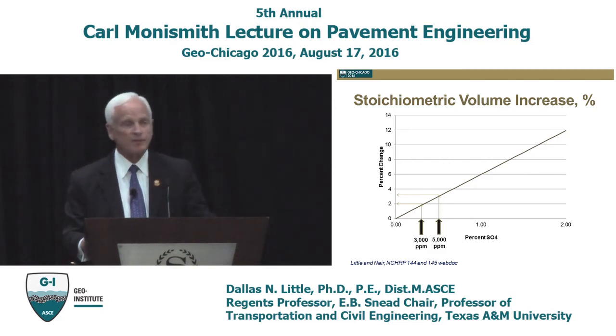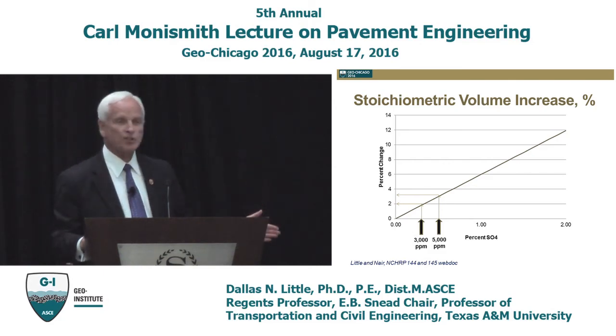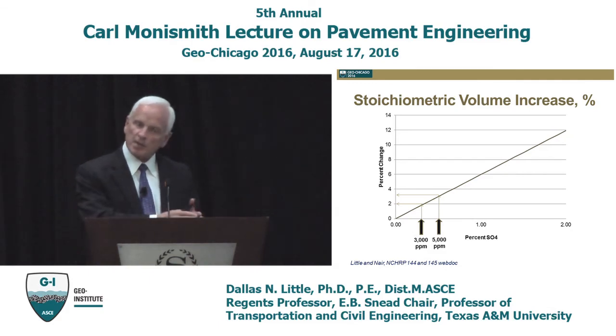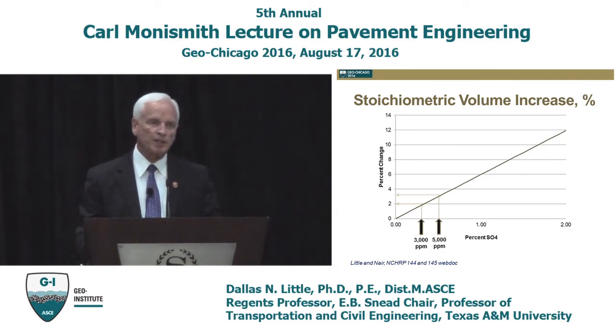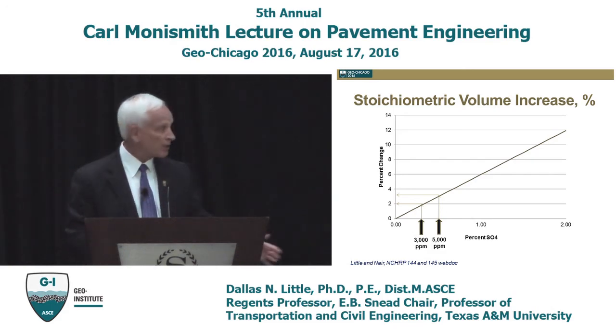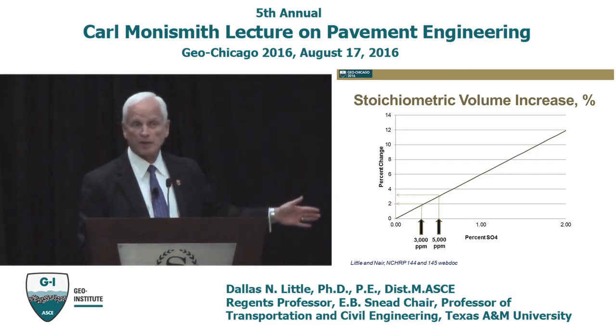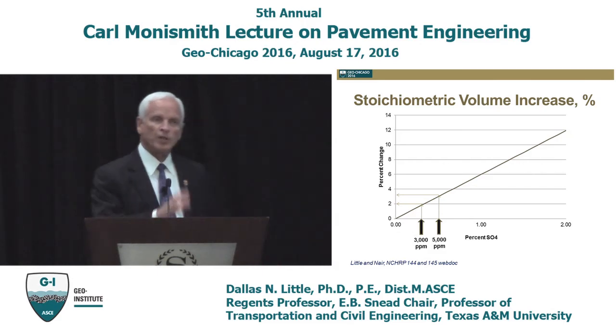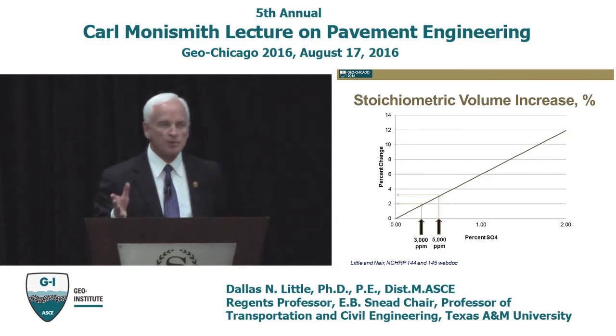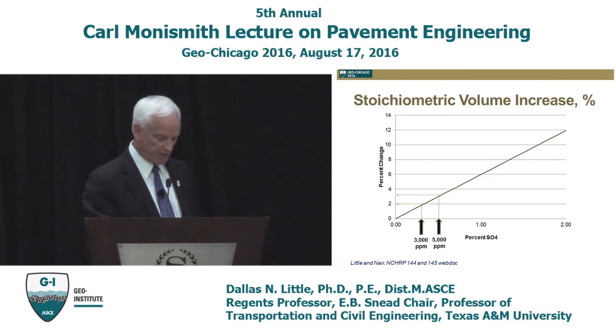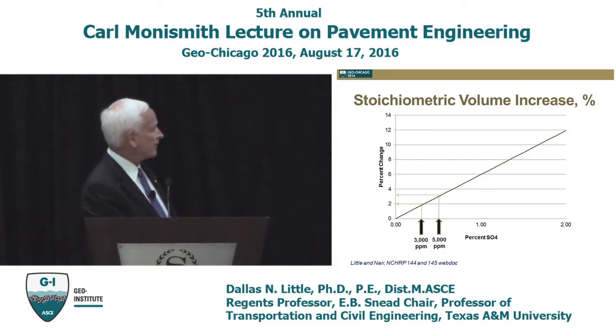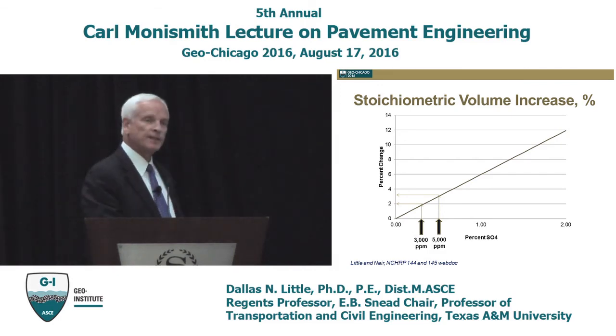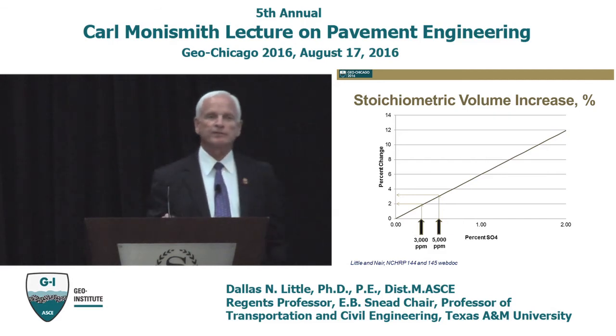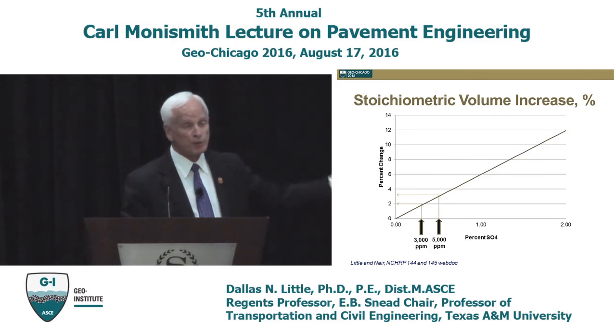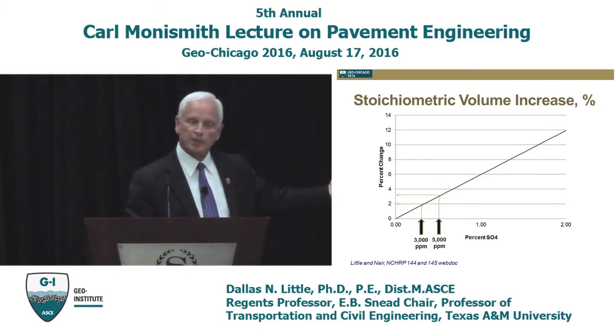So that's pretty safe. If you go up to between 3,000 and 5,000 parts per million, you become a little bit more risky, but generally your system can accommodate that level of ettringite. You go above that, and you really have to do some special things to guard against it. So we use basic material science, geochemistry, for the phase diagram, coupled with stoichiometrics to figure out those initial values. Back when we were dealing with the Denver airport in the mid to late 80s is when we were trying to come up with this stuff. And it's still pretty valid.